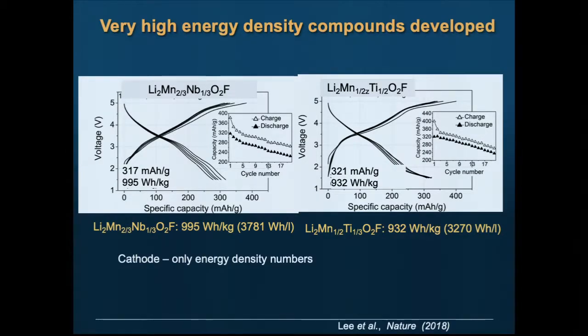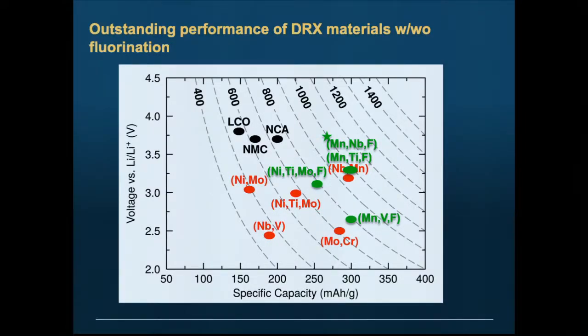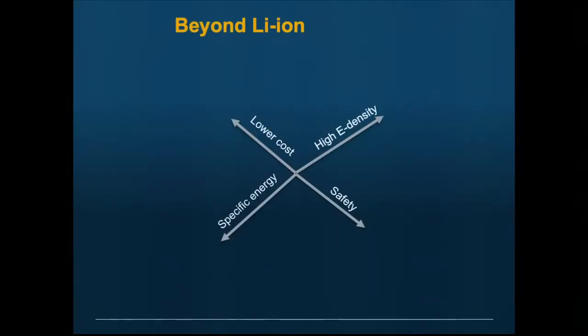We've been able to go to really high energy contents, almost approaching 1,000 watt-hours per kilogram, which in contrast, today's best cathodes are about 650 to 700 watt-hours per kilogram. And we can do it with fairly cheap elements like manganese and titanium, right? This one is manganese and niobium, which is not the greatest. It's in a similar situation to cobalt, but this one is actually very good. Okay, let me skip that. So we've unlocked the periodic table.